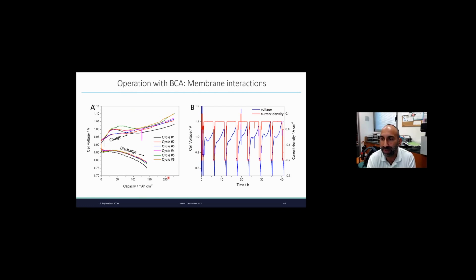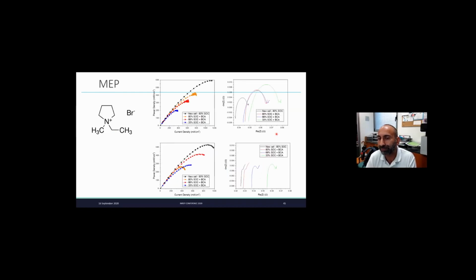But, and there's a big but that we published in Journal of Power Sources this year, when you try to cycle this kind of bromine complexing agent, they stick to the membrane. What we see here is the charge discharge with one of these ethylpyridinium. We see some overpotential, and after some time the overpotential keeps growing, and you can't cycle anymore.